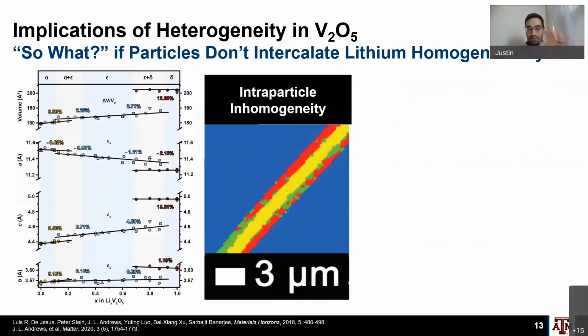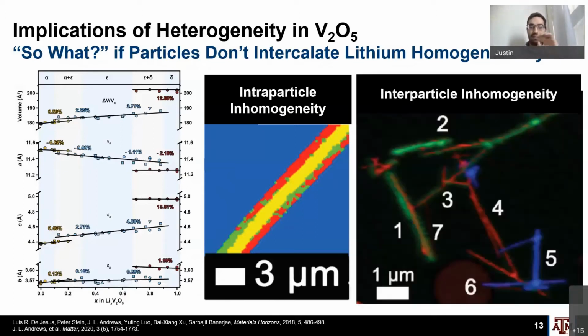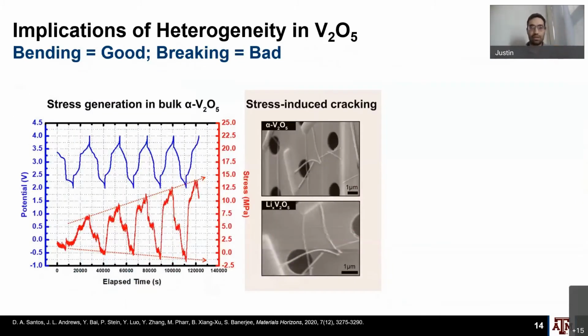And before I get into talking about how we've come to address these things and some different methods that we've worked on, ultimately the problem goes beyond just the sluggish diffusion kinetics, the electronic and the ionic. As this lattice mismatch takes place, as these phases evolve, there's actually significant intraparticle inhomogeneity and also inhomogeneity across particles in these cathodes as they are cycled. And you can imagine that this creates a lot of intraparticle and interparticle strain that can lead to delamination and fracture of the materials, which I'll talk about in a little bit. And so you can see that here.